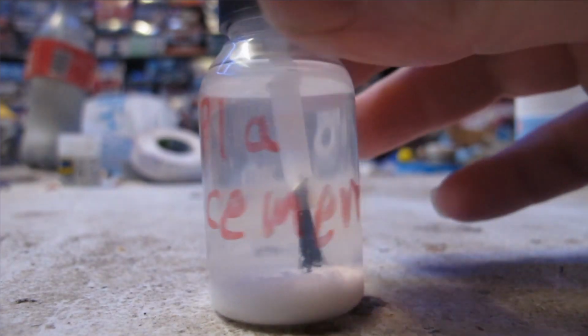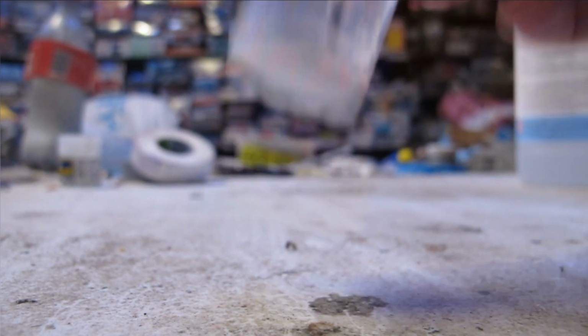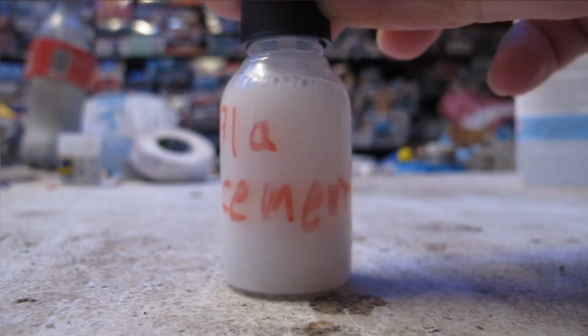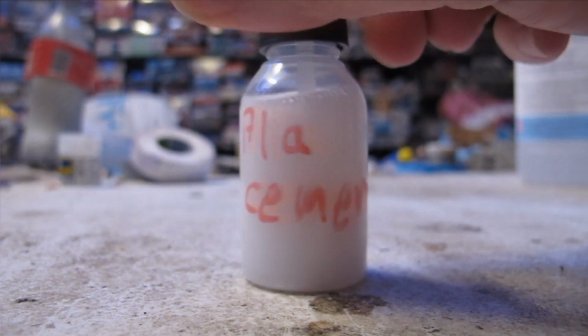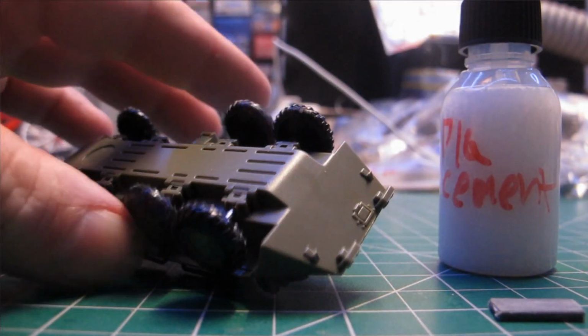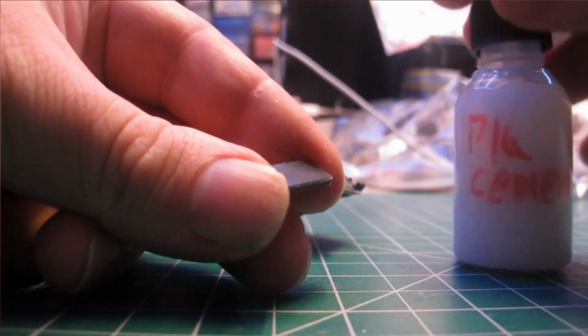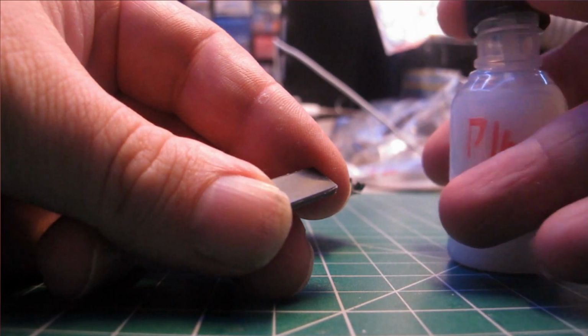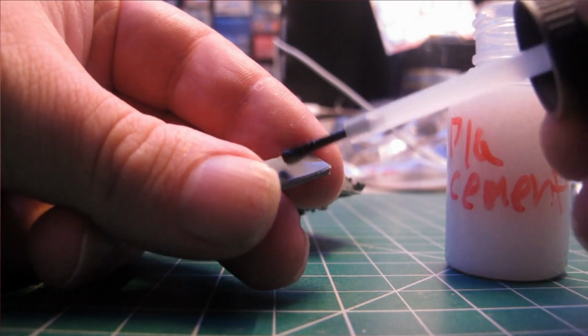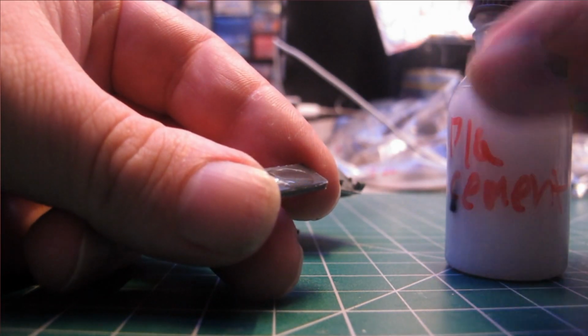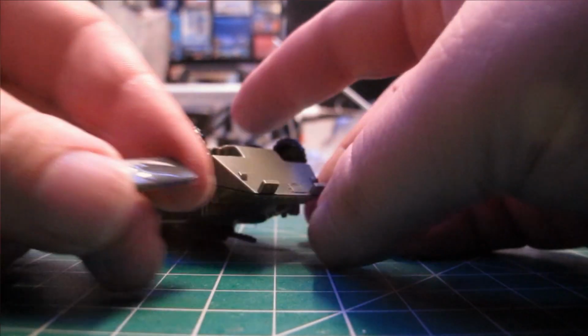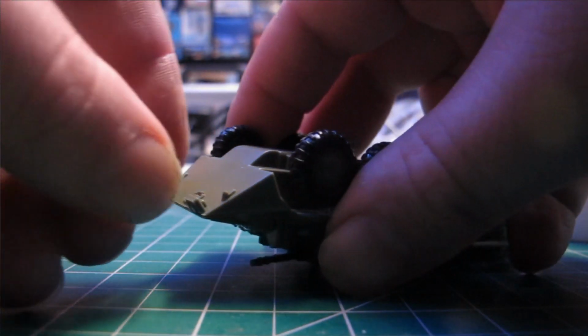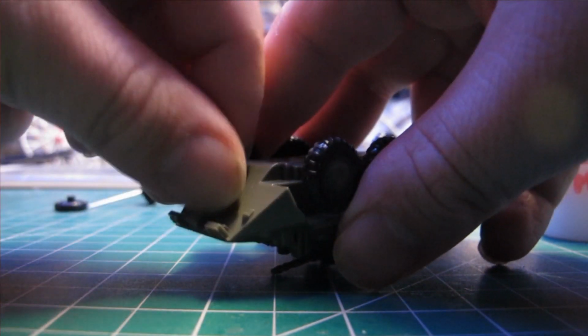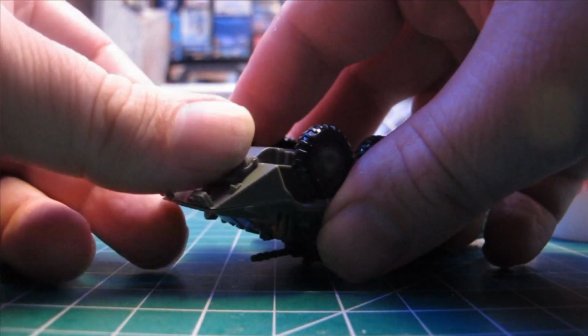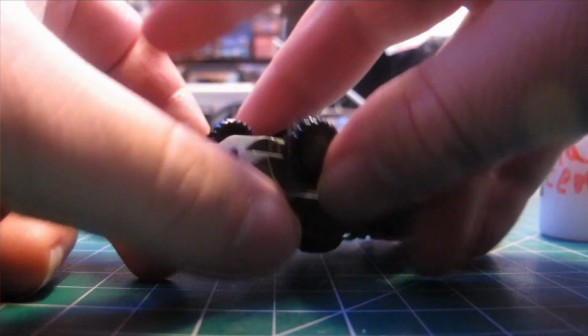Raw styrene comes clear. I decided to use white from some runners. With a 50-50 mix of MEK and acetone, a strong solvent mix, in a matter of 2 hours the plastic completely liquefied. Interestingly, I learnt the resin separates from the liquid very quickly and requires shaking before use. Including evaporation, this may explain why plastic cement gets thicker and thicker over time with use.